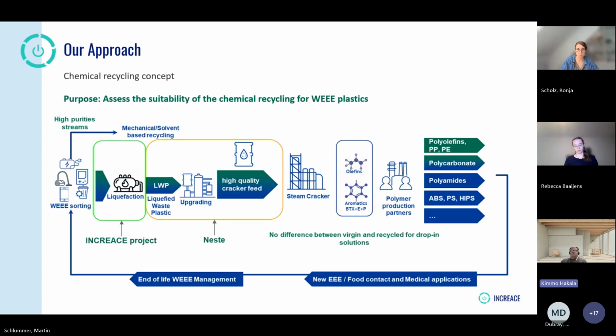The next slide is showing our approach. From the left, we take some sorted fraction, which is not good enough for mechanical recycling at least. And then in this study, we have done this liquefaction, and the target is then from the liquefaction to take the fraction which is suitable for the steam cracker, but between the liquefaction and steam cracker, there needs to be also some purification step, meaning upgrading. And then from the steam cracker, you can get olefins, which you can use in the synthesis of new polymers like polyolefins or any other polymers also. Next.